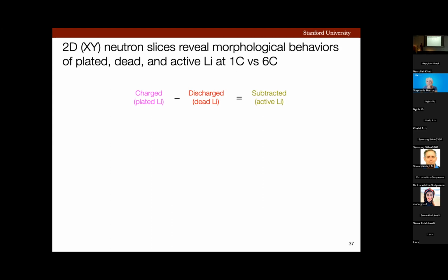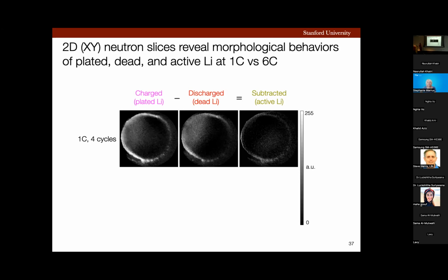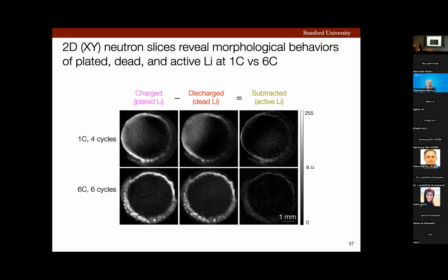Then I subtracted my 3D data of the charge from the discharge tomography to get a calculated subtracted data set, which gave me my active lithium. This is the lithium that went back to the cathode during the discharge process. Now let's look at the images. You would see in these images brightish deposits around the edges of the graphite electrode at 1C. Now, if we compare this data with that of a 6C, you can see a clear morphological difference. For example, at 6C first, qualitatively, we are looking at a more complete circle, which shows that qualitatively there's higher amount of plated lithium than at 1C, which is expected.